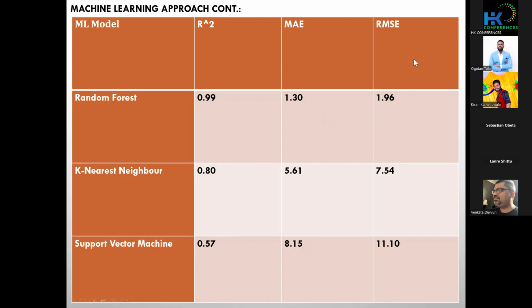And also random forest has the lowest value for root mean squared error, which is 1.96 against 7.54 for k-nearest neighbor and against 11.10 for support vector machine. So this research that was conducted by me simply means that random forest was a good machine learning model to use to predict compressive strength of admixture mixed concrete.